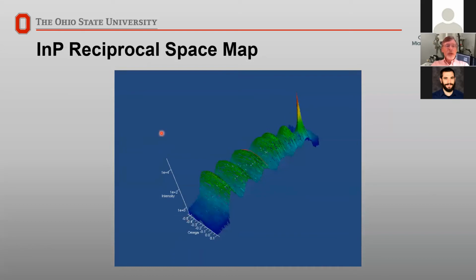And the thing to note here is that this is a log scale, and we're looking at about 5 to 6 orders of magnitude between the intensity in this peak and the intensity in these hubs. So it takes a little while to collect the data to get sufficient statistics that you get a nice film. But then this is telling you now the quality of your growth. And with that, I think I'm going to end here on talking about X-rays.